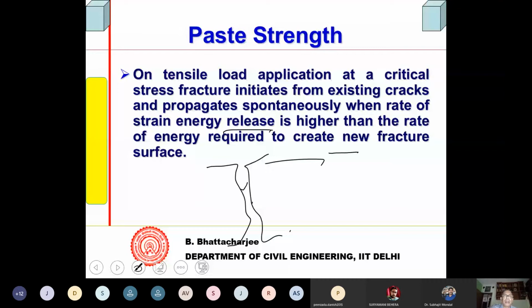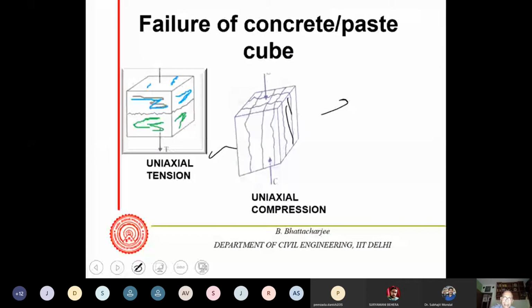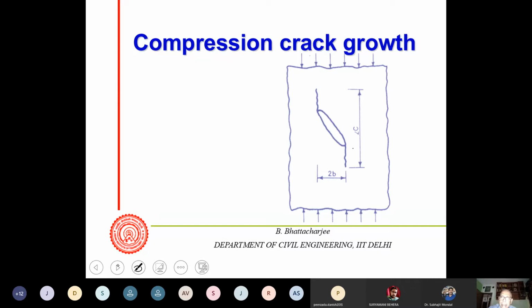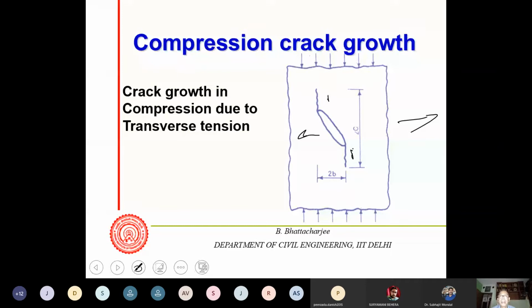Now we know the failure of a cube under tension will be something like this. Uniaxial tension, uniaxial compression, you will have cracks along the transverse direction because tensile forces are acting. Uniaxial compression will be something like this. In uniaxial compression, cracks are parallel to the load. Actually, there is tension along the transverse direction, Poisson's effect, and it can take much less tension. The mechanical bond is not there, so therefore it will fail.